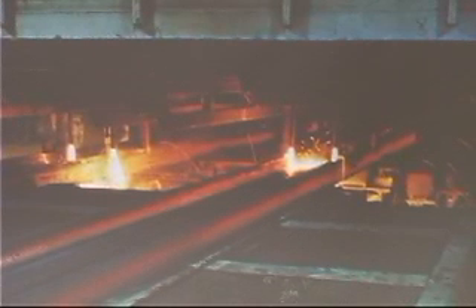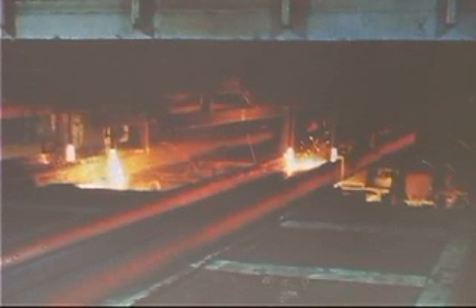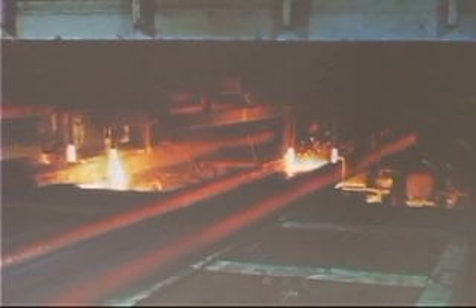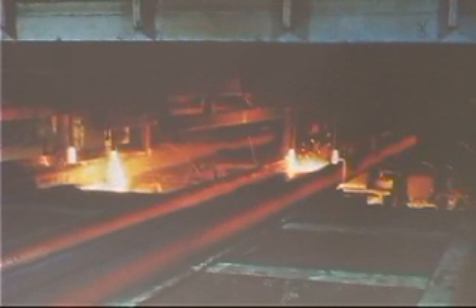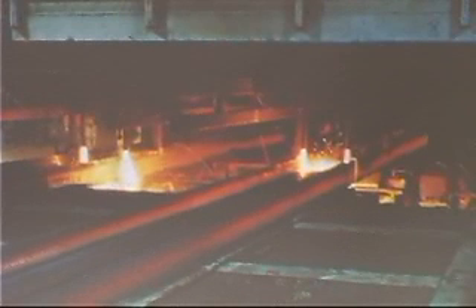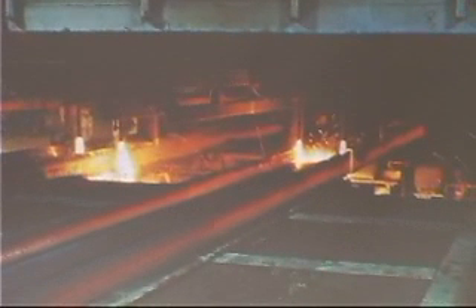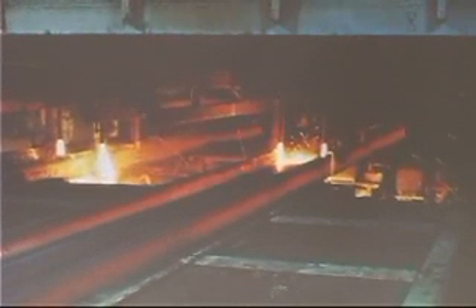So now you end up with, instead of a rectangular piece of what we call a billet coming from an ingot, they actually cast something that's already almost in the final shape of the I-beam they want. Instead of 28 passes when you're starting out with a rectangle, it only takes 9 to 11 passes to end up with the final I-beam. Not only that, they can roll thinner gauge I-beam than if you start out with a rectangle. Why? Well, in 28 passes, the steel's got a lot of time to cool. In 9 to 11 passes, the steel stays hot, which means you can roll it down thinner.